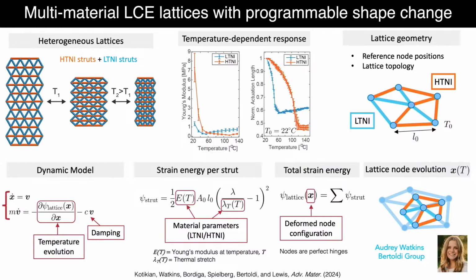But in order to feed the model, we did experiments to characterize the stiffness as a function of temperature for both of these materials in printed form, and also their actuation lengths as a function of temperature. So again, the higher TNI material has a higher actuation percentage, but also requires a higher actuation temperature. The low TNI material triggers earlier. With this dynamic model, they are inputting these values for the Young's modulus, which we've measured as a function of temperature, and the normalized actuation length, also a function of temperature. And from that, then, they can take an initial configuration and predict the final configuration after all this shape morphing has occurred, sequentially low TNI first, then high TNI.